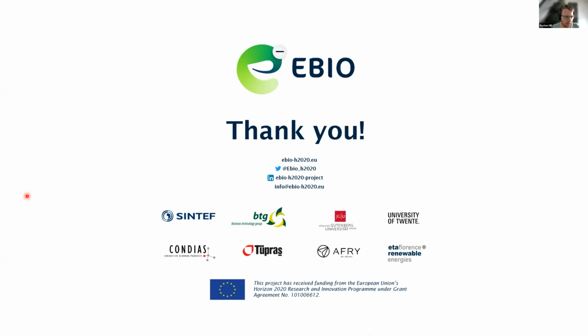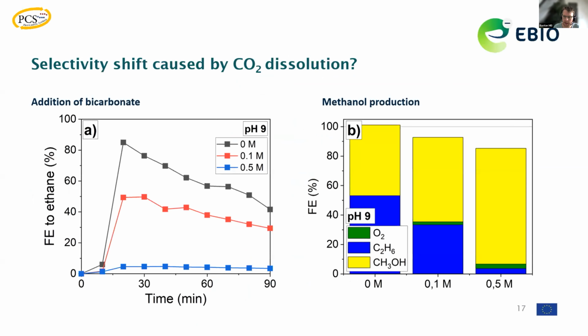No, we haven't measured any hydrogen peroxide yet, but we of course are aware that there is also a current trend in hydrogen peroxide formation anodically, and there is also of course the carbonate-bicarbonate couple being involved. So if I just go back to this slide, of course we do not account yet for the full 100% Faradaic efficiency, and it might be possible that there's some hydrogen peroxide being formed here as well. That still needs to be checked. So, in short, we haven't checked yet.